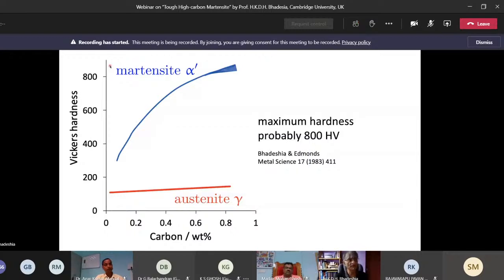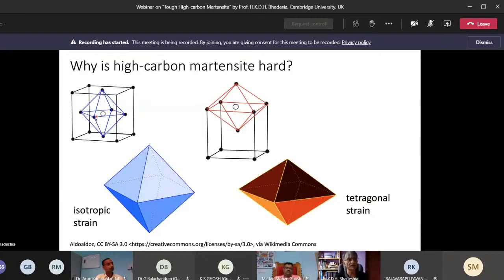Here, I'm showing you the unit cell of austenite, and this is the location of the carbon atom inside an octahedral interstice, which I've drawn out over here as well. The thing to notice is that this is a perfectly regular octahedron. In other words, the distance here is the same as the distance here, which is the same as the distance here. So when you put a carbon atom inside the octahedral interstice in austenite, you get a uniform expansion.